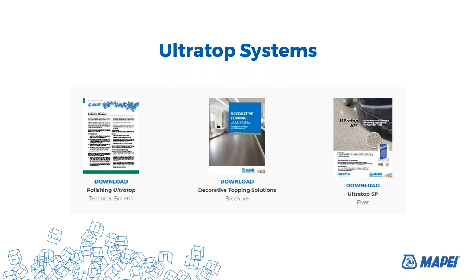The presentation is done. I'm ready for questions. Thank you, Maurizio. We do have some questions. The first is: Is CSP number 3 the minimum guideline, or are other CSP conditions acceptable for the installation of ultra-top natural? Thank you for the question. CSP number 3 is what we are recommending because we are working with the epoxy primer. The thickness of the epoxy primer is important — with that kind of thickness, we are sure the penetration of the epoxy primer can go into the concrete slab if the slab is at CSP number 3.